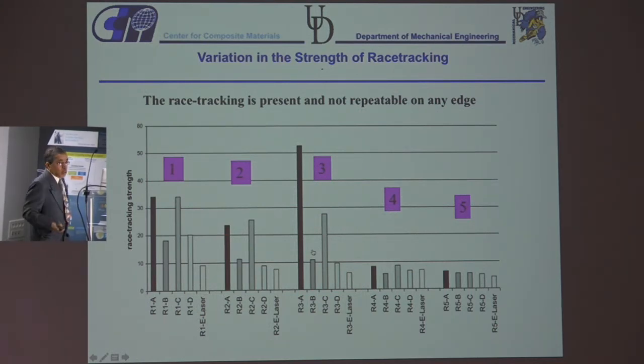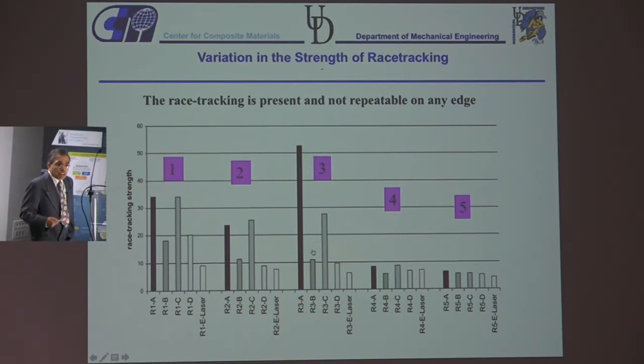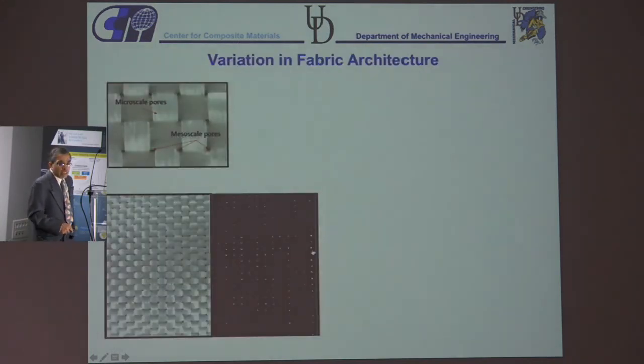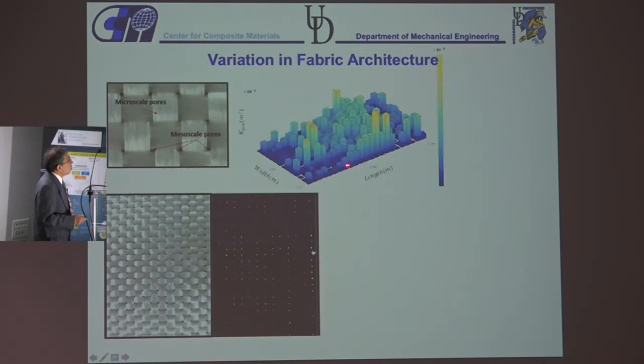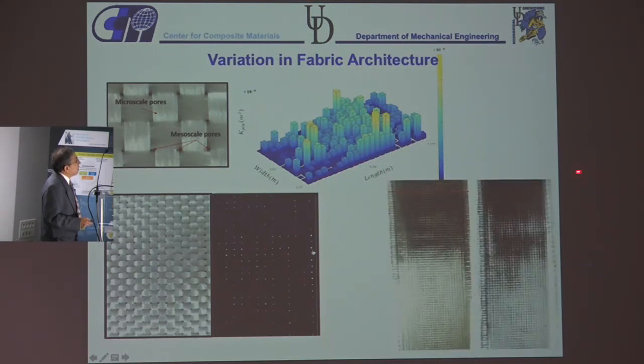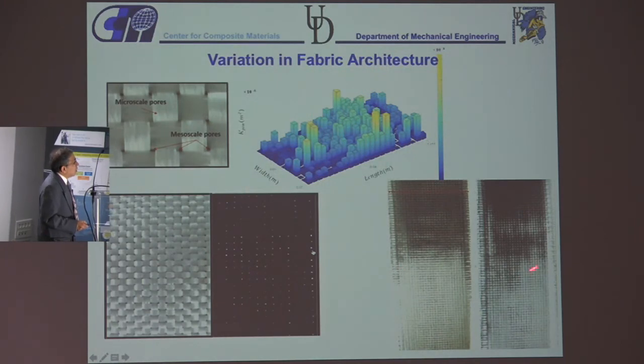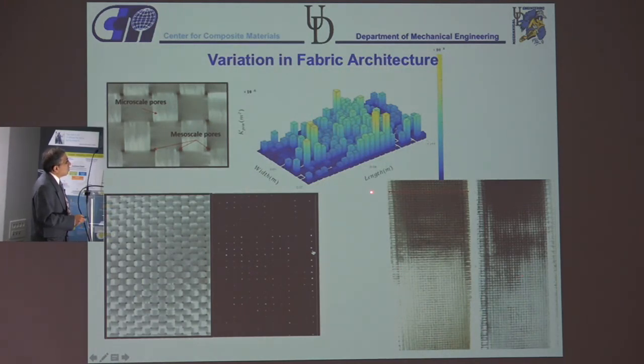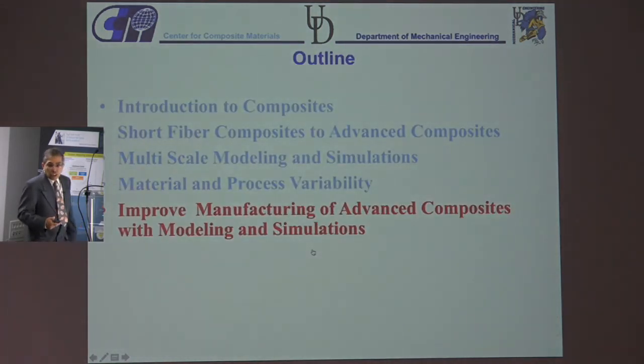So what it told us was, you can't fight race tracking. It's going to happen. You can't have skilled labor that's going to do it. So instead of fighting it, let's figure out, when we have race tracking, what is the great place to put the inlet and the exit. The other thing we talked about was when you have these pinholes, and they can be, again, different for different fabrics. So this is the pinhole distribution in this fabric, the diameter of the pinholes. And you can see, because of those pinholes, you get these sort of flow fronts at the bottom, because the resin, when it comes from the top, wherever there is a pinhole, it comes to the bottom and then starts to spread around. So we have to be able to even address those kind of issues.